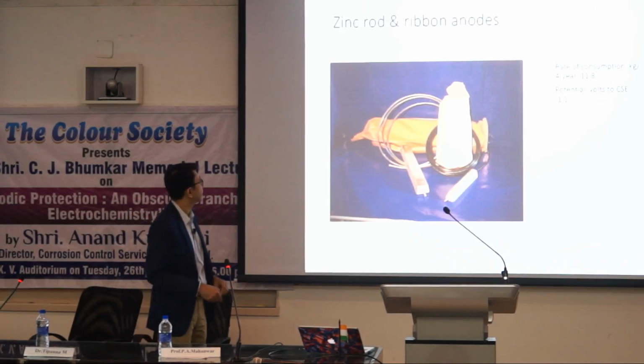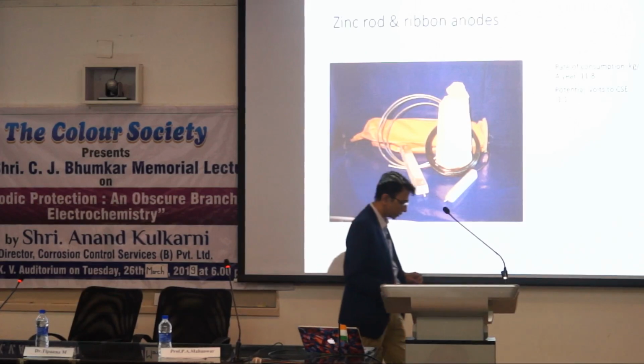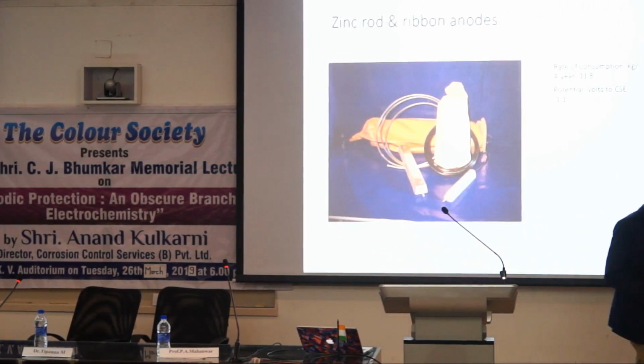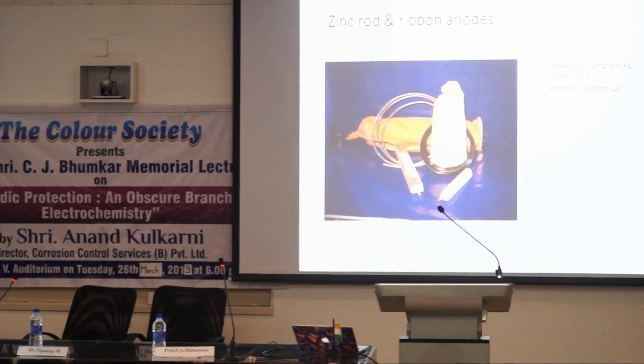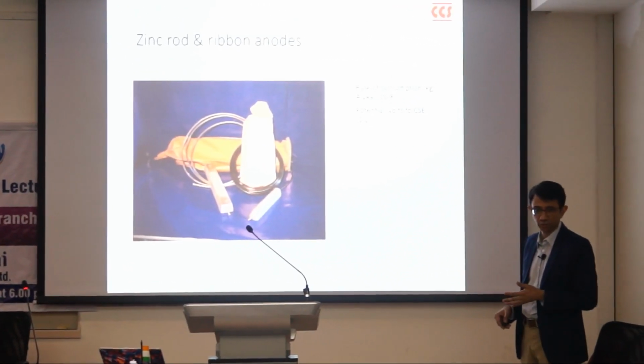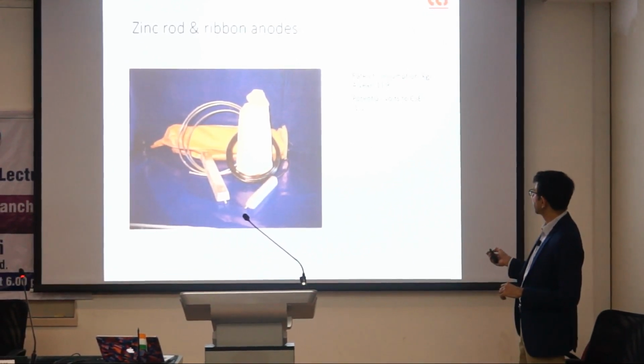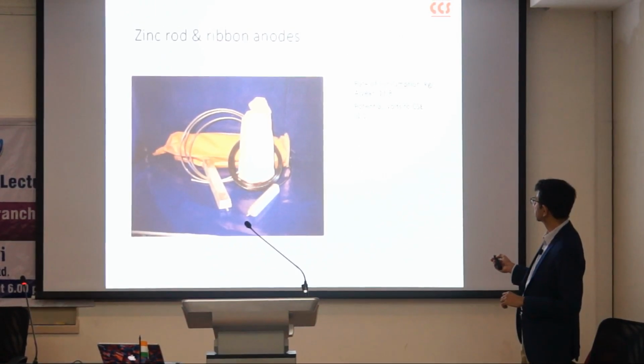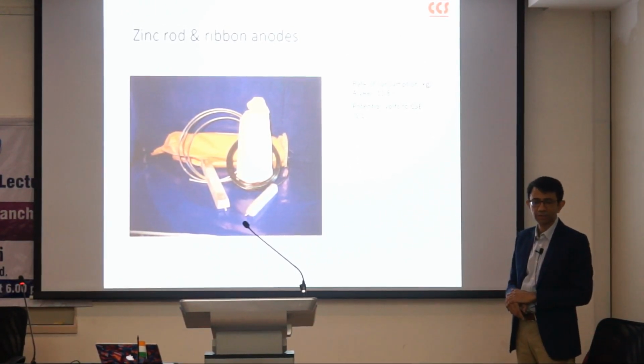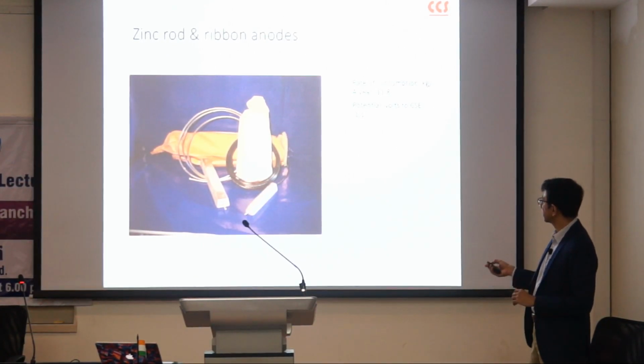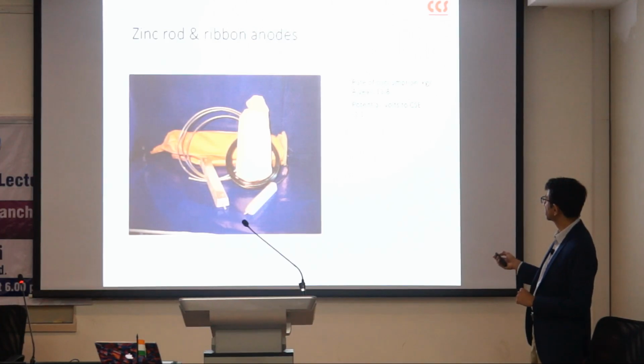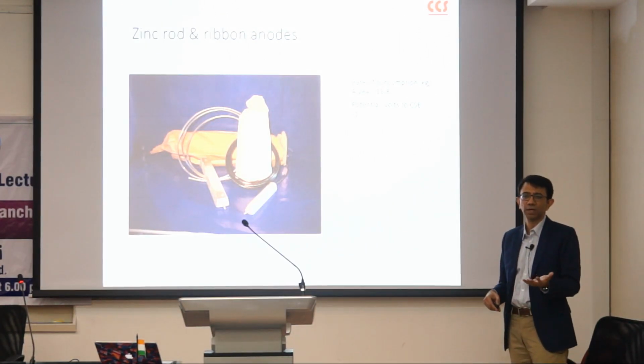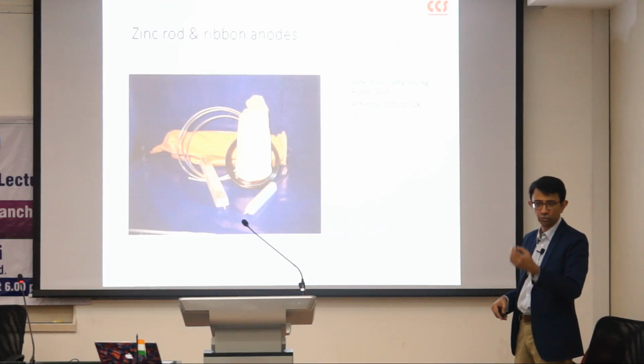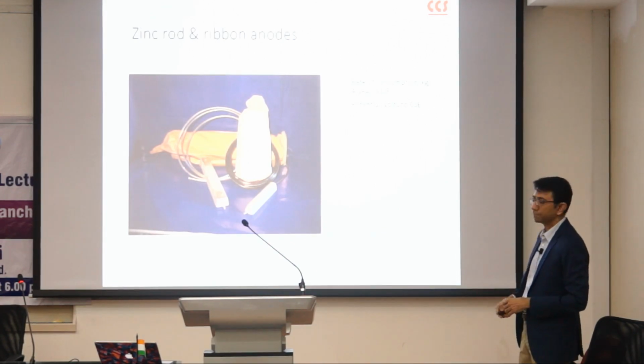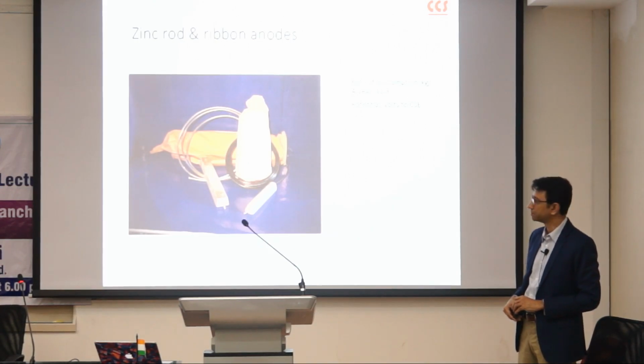I have a couple of slides up here to talk about the galvanic anode. So, zinc is of course the historically famous cathodic protection anode. As I talked about earlier, Sir Humphrey Davy used zinc ingots to protect the copper clad ships. Its potential to what is called a copper sulfate electrode, which is a reference electrode, I will talk about it in a bit more detail a little later, is minus 1.1 volts, and its rate of consumption is 11.8 kilograms per ampere year, which means that if you have 1 ampere of current being discharged from a zinc plate or a zinc structure for 1 year, then 11.8 kilograms of zinc would get consumed.